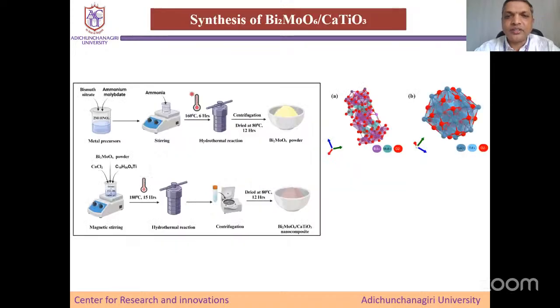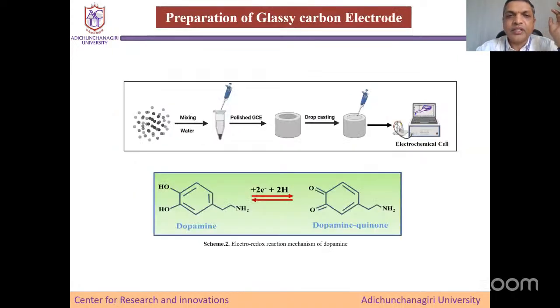This is the synthetic methodology which we have adapted. Again, it is a metal precursor, stirring, and then a hydrothermal reaction to get bismuth molybdenum oxide. And then we have used the same thing with bismuth molybdenum using calcium chloride, with a hydrothermal reaction, then centrifugation, and ultimately we get the nanocomposite. And this is the structural elucidation of the nanocomposite in order to confirm its formation.